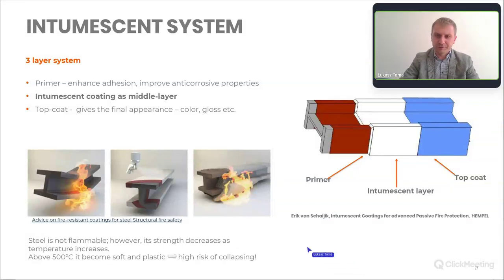And if we put the intumescent system, during the fire, as I said, they create a protective layer of char, which prevents the heat transfer. We can extend the time for reaching 500 Celsius degrees. So it's essential to also extend, for example, as I mentioned, this kind of emergency actions and so on.